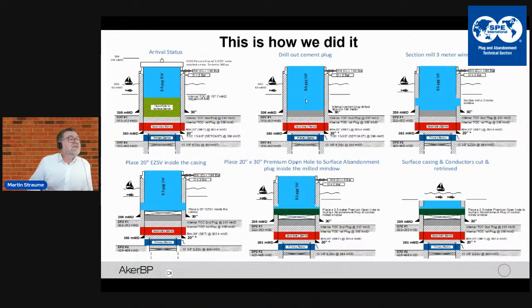So we actually drilled out some of that cement to get deep enough so we could log that we had decent cement on the outside. And then we actually made a section mill in the 20-inch out to the 30-inch, and then we scraped the inside of the 30-inch to make sure that we had removed anything that had to do with mud or spacer or old cement stuff that could potentially cause a leakage.